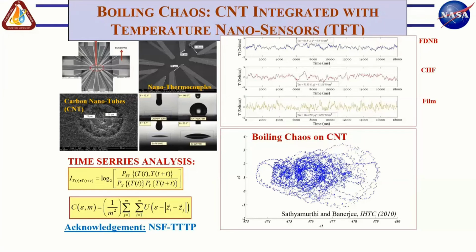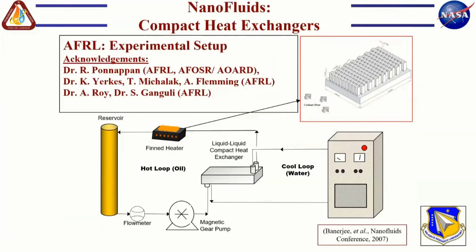Or in other words, if I have a nanothermocouple measuring temperature on a surface for a long time, just by looking at the type of fluctuation I'm getting, I can characterize the type of boiling regime that I can get on this heater surface. Now, coming back to this idea of nanofins as a thermal capacitor.